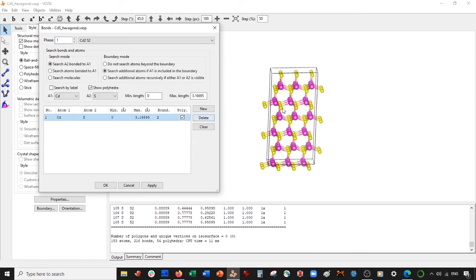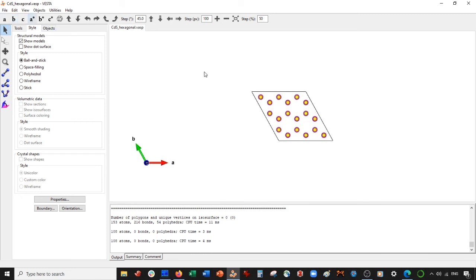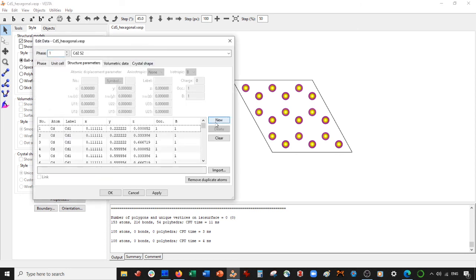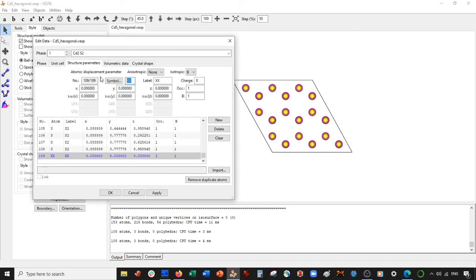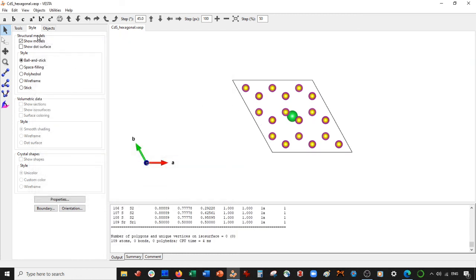I'm going to delete the current cadmium sulfide bonds and press C to look down. To build a quantum dot from this, I go to Structure Parameters from Edit and add a new atom. The atom I like to add is a strontium atom. I place it at the center of my cell using fractional coordinates, so I put all of these as 0.5. Here shows up the strontium atom — select OK.